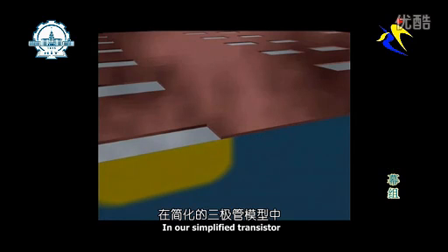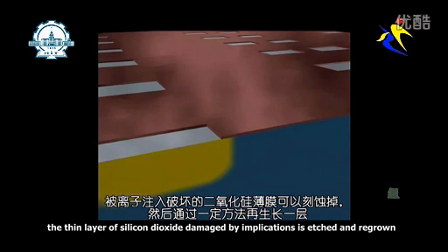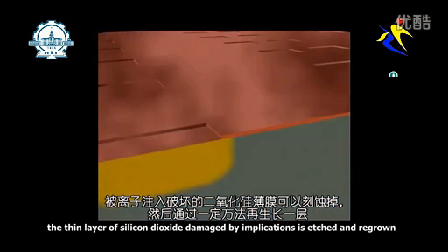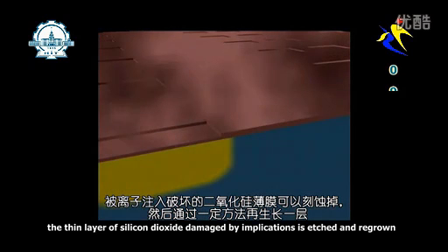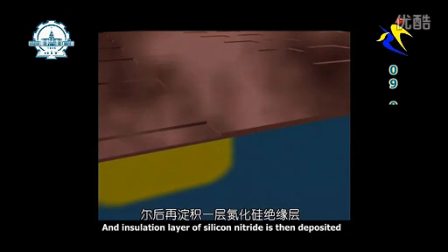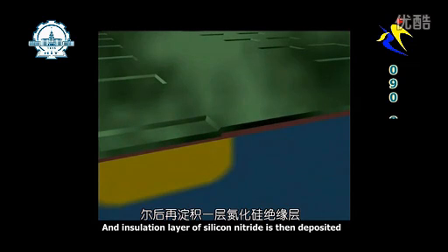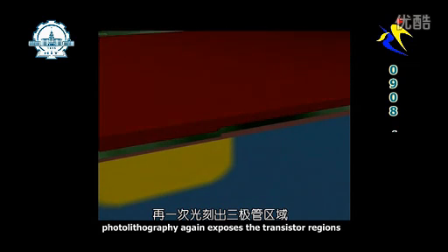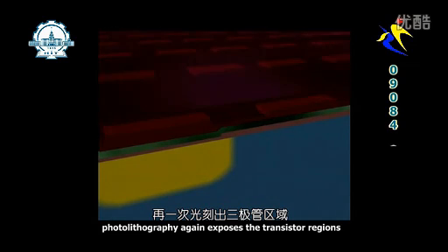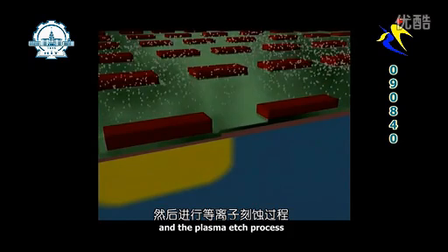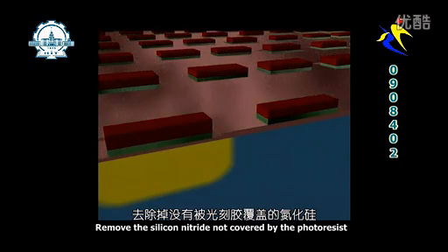In our simplified transistor, the thin layer of silicon dioxide damaged by implantation is etched and regrown. An insulation layer of silicon nitride is then deposited. Photolithography again exposes the transistor regions, and a plasma etch process removes the silicon nitride not covered by the photoresist.